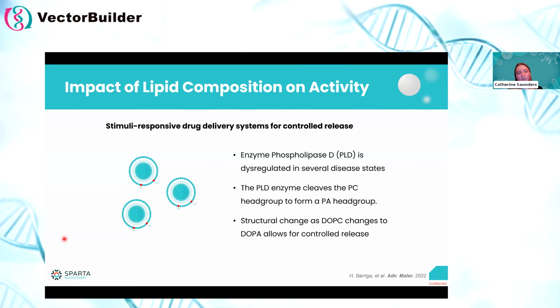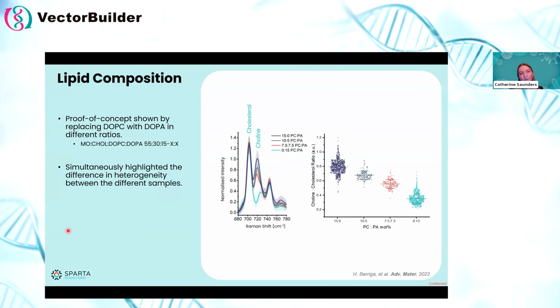So what you can do is take these responsive lipid nanoparticles, incubate them with the enzyme, and you'll see a change from the PC to the PA head group. And you can then use this for a controlled release application. So just to show you how SPARTA was used here, we can take the same workflow as before.